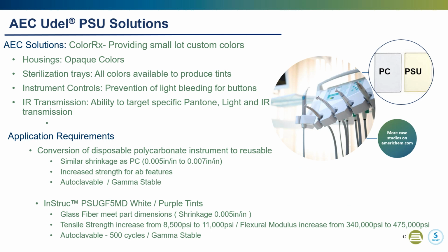The 5% glass helped to meet the critical dimensions by lowering the shrink from a range of 5 to 7 thousandths inch per inch to a more consistent 5 thousandths inch per inch, and also improving mechanical properties. Now we move up to Radel, also an amorphous material.